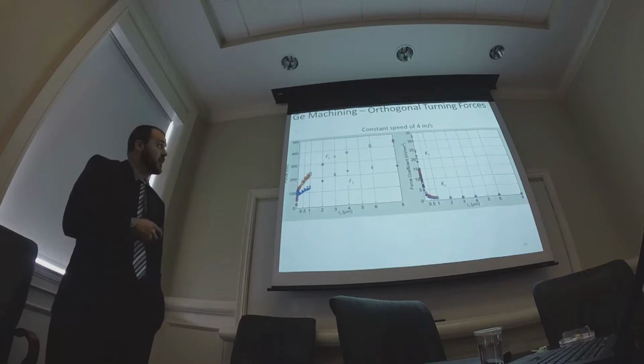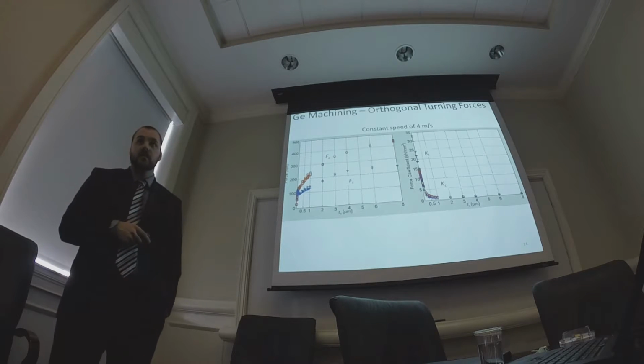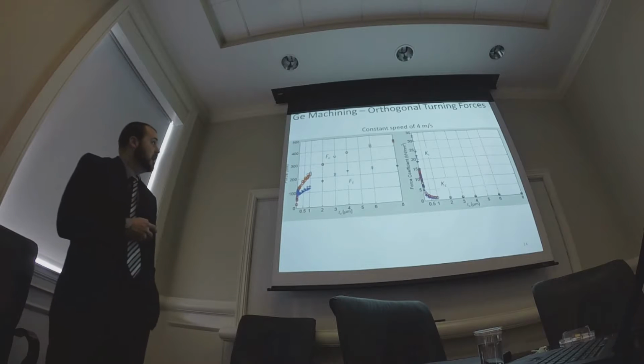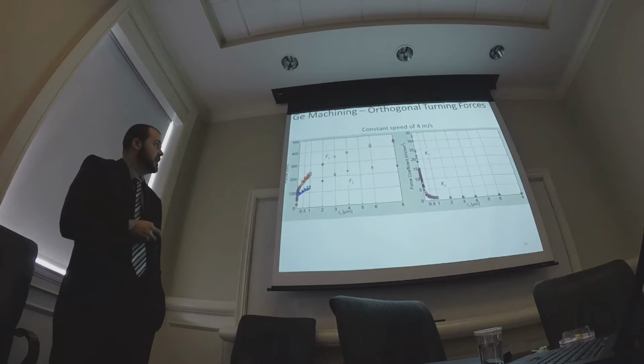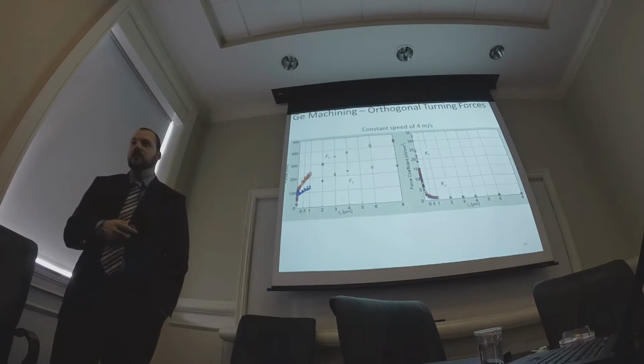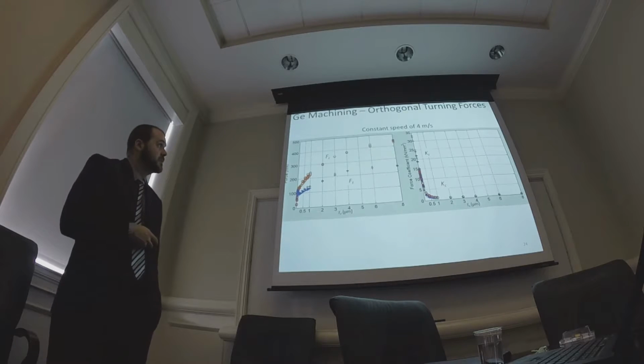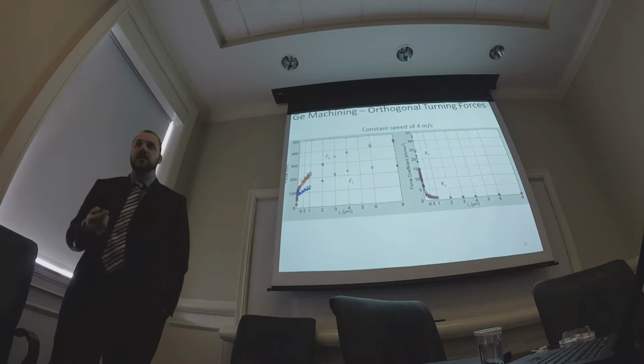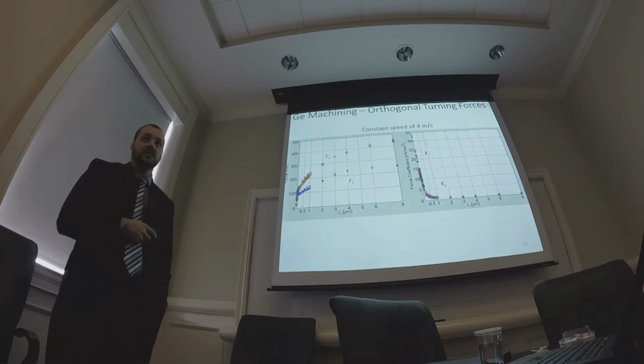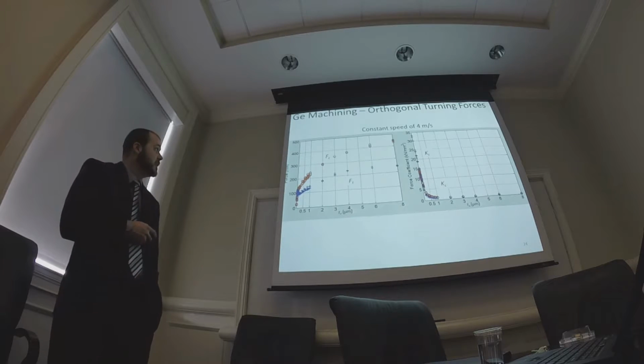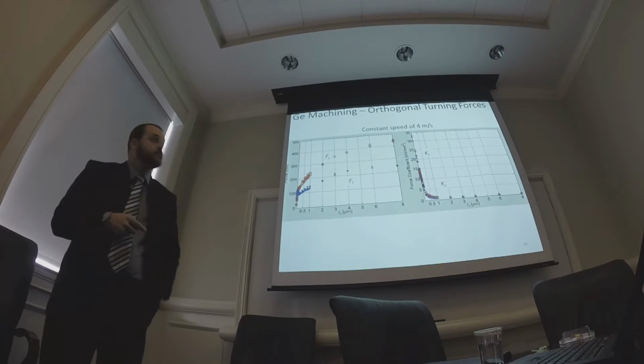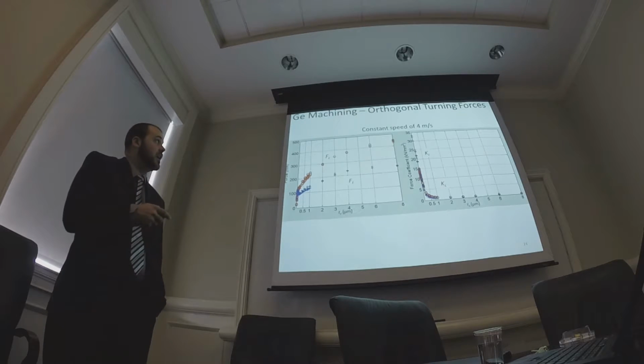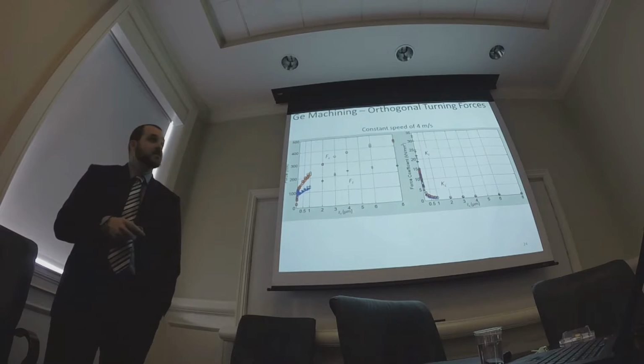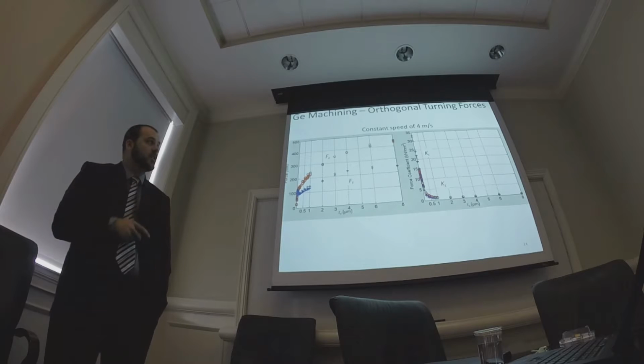Here are the results from the germanium at a constant speed of 4 meters per second, same as where we did the RG-26. We don't see that drastic drop-off that we saw in the RG-26. It's still not completely clear why the RG-26 is dropping so drastically, but we do see the force start to level off a bit. This tells us that if it's acting like the RG-26, we're starting to get more brittle fracture out here, so the force is leveling off.